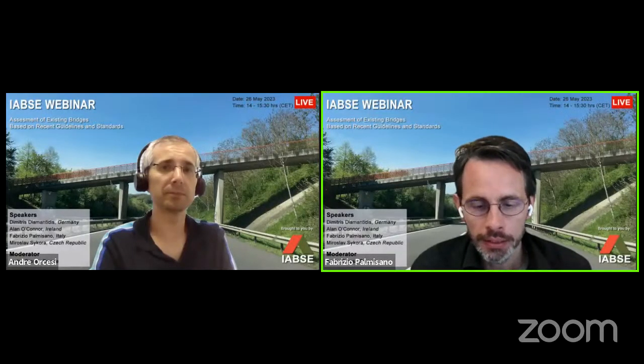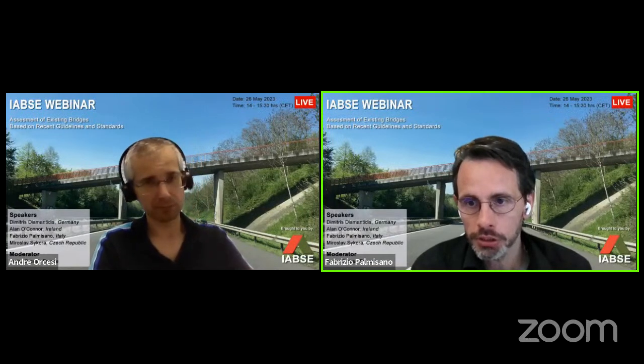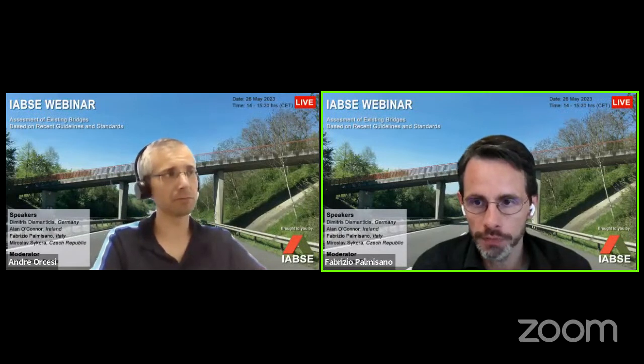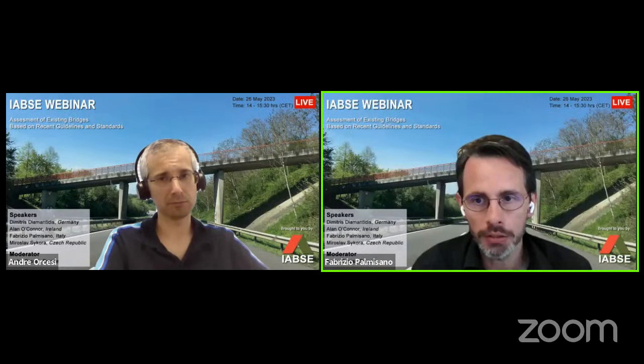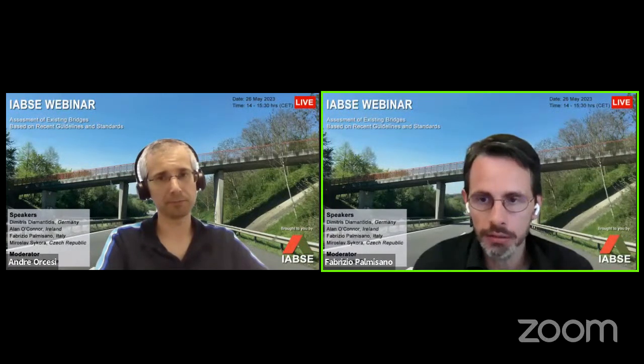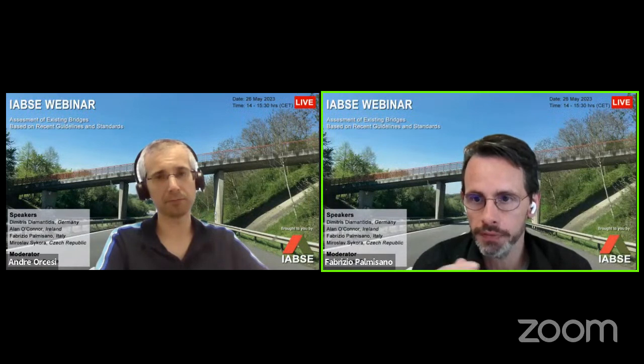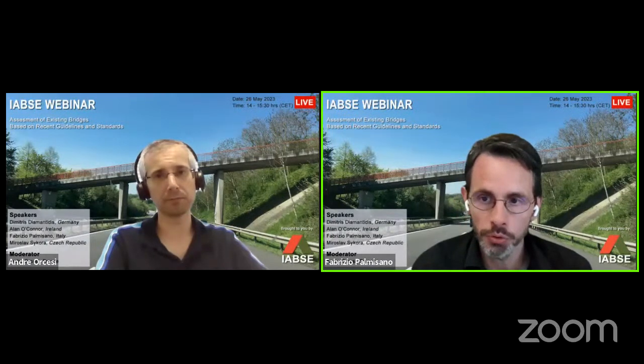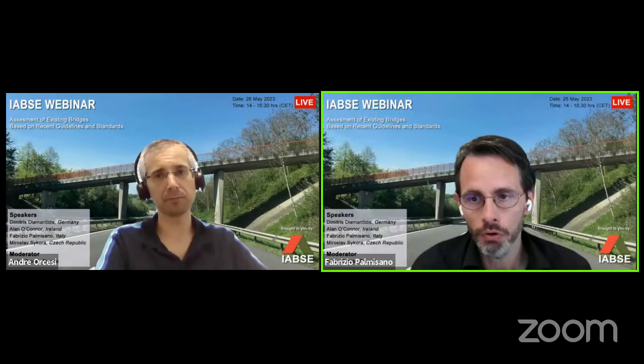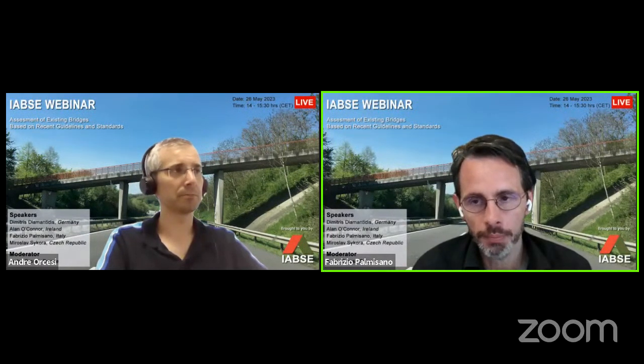The variability of strength of both concrete and steel is taken into account in the characteristic value and in the partial factor. So when we update the partial factor, we consider also the result of the coefficient of variation taken from the in situ test. The aim of the kappa value is different because the kappa value considers the difference in resistance if we have a sample taken in situ and a sample taken during casting, because in situ we have the effect of curing, the effect of different curing, of consolidation of fresh concrete, the anisotropy, the effect of coring that we don't have on the sample that we take during construction. So there is the need to have a kappa value for concrete, and we don't have the need to have a kappa value for steel. So the response is that we don't have a kappa value for steel reinforcement.